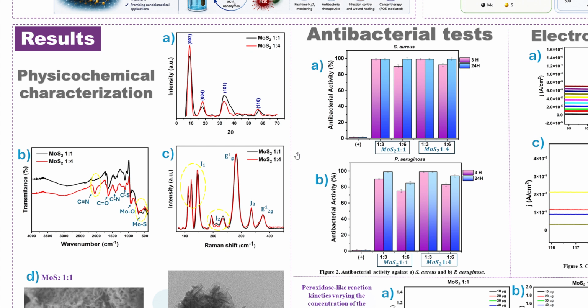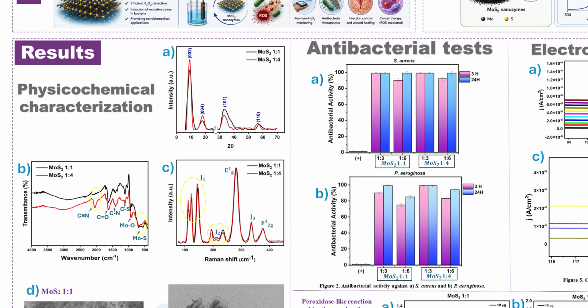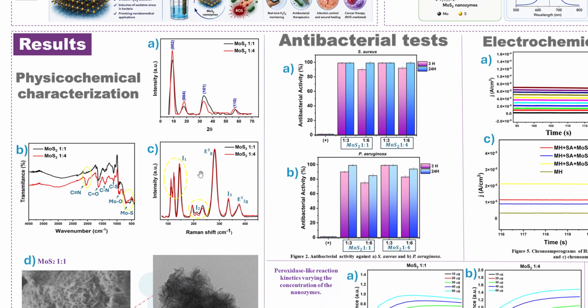Moving to results, the physicochemical characterization confirmed the successful formation of nanostructured molybdenum disulfide. The X-ray diffraction patterns show the characteristic reflections associated with molybdenum disulfide, while FTIR spectroscopy showed vibrations related to the molybdenum-sulfur bonds. More importantly, the Raman spectrum showed the characteristic E2g1 and A1g vibration modes of molybdenum disulfide. Differences between the samples can also be observed, particularly in the low wavenumber regions, suggesting structural modification associated with the different synthesis conditions.